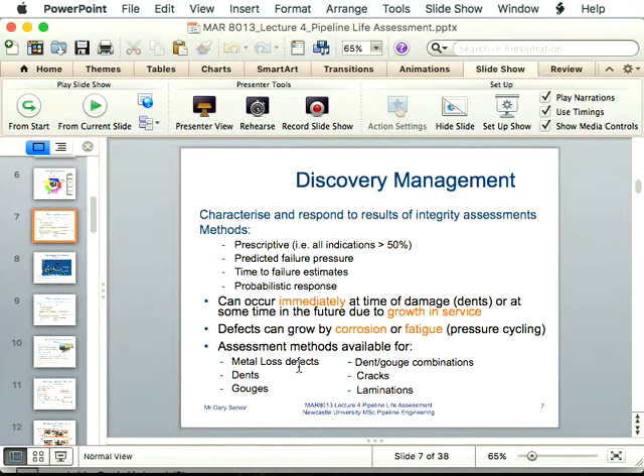Dents do potentially two things to the pipeline that we don't want it to do. First of all, we have this geometry discontinuity. The pipeline's sitting there quite happily as a thin tube under the ground, which is the perfect shape for resisting pressure. Then a dent is there, and that causes a discontinuity, which causes stress concentrations. So the stress isn't predicted anymore by PD over T. You get a big concentration in the dent because of the profile. So if you've got a defect in there, it may be subject to 2 or 3 times the stress that the main pipeline is in.